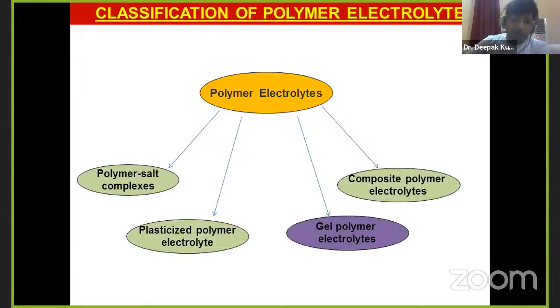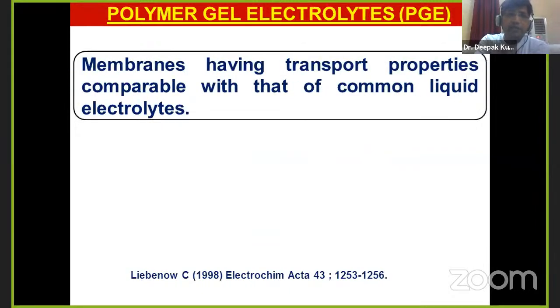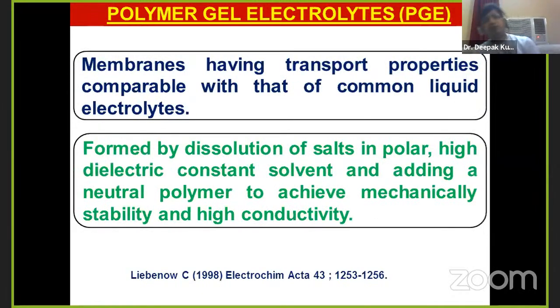That's why people are trying different kinds of polymer electrolytes. The polymer electrolytes can be polymer salt complexes, plasticized electrolytes, gel polymer electrolytes, and composite polymer electrolytes. In this presentation, we will be focusing on gel polymer electrolytes and some investigations on that. Polymer gel electrolytes are membranes having transport properties quite comparable with those of liquid electrolytes, and such an electrolyte is formed by the dissolution of salt in a polar high dielectric solvent and adding a neutral polymer to achieve mechanical stability and good conductivity.